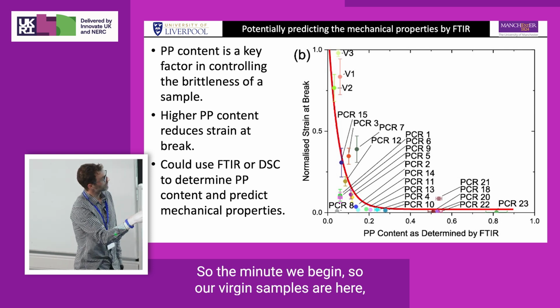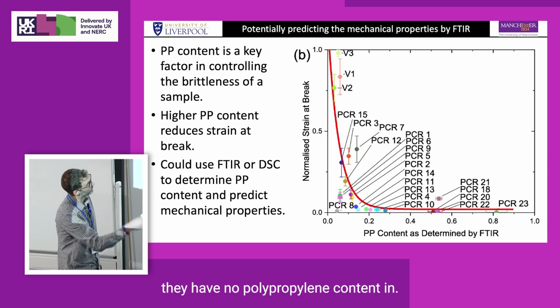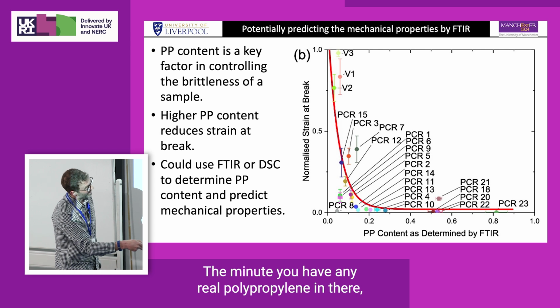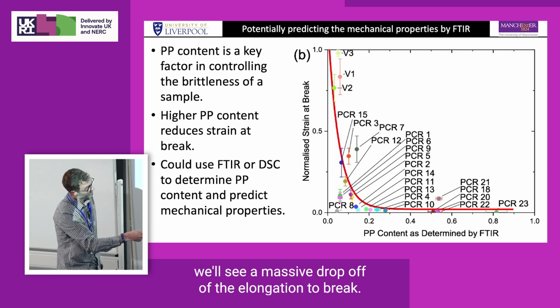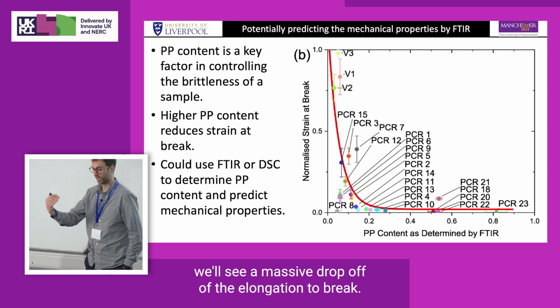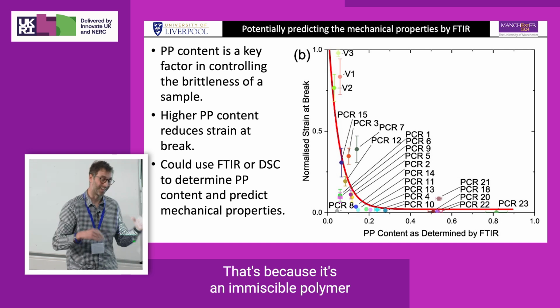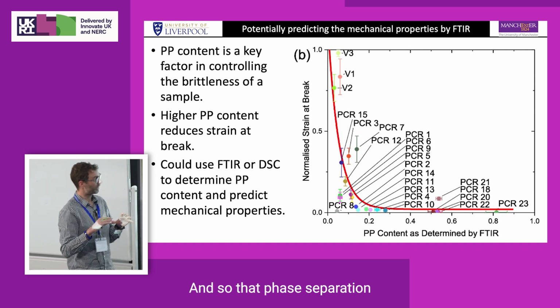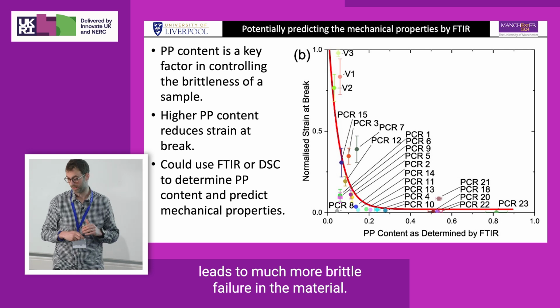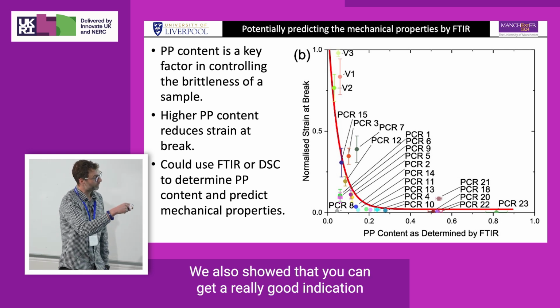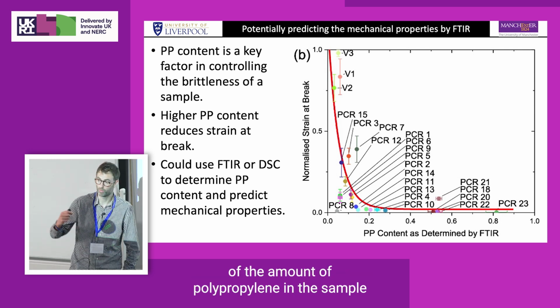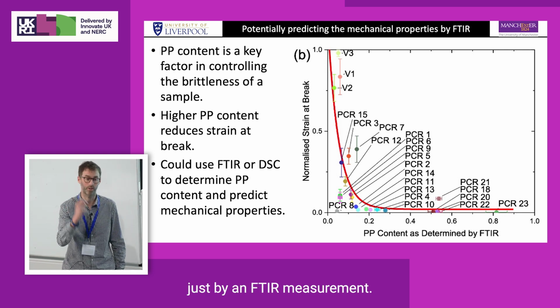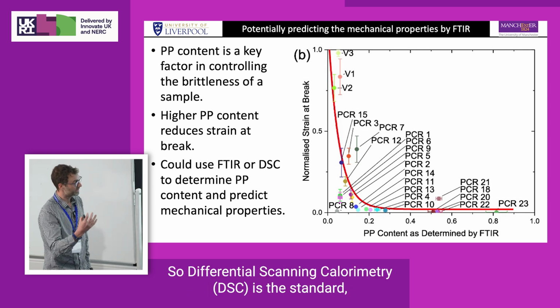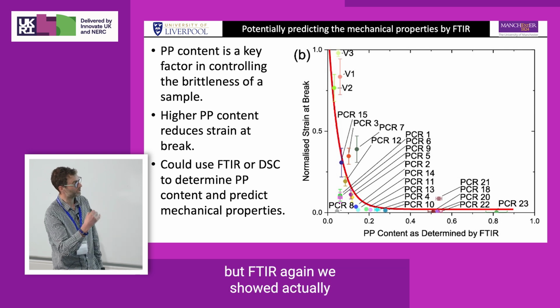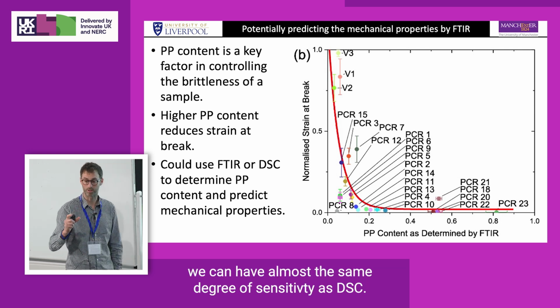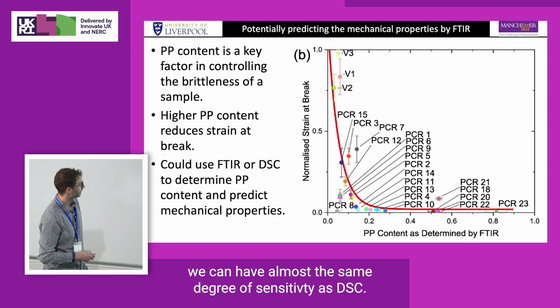So the minute we begin, our virgin samples are here, they have no polypropylene content in. The minute you have any real polypropylene in there, we'll see a massive drop off of the elongation to break. That's because it's an immiscible polymer, and so that phase separation leads to much more brittle failure in the material. We also showed that you can get a really good indication of the amount of polypropylene in the sample just by an FTIR measurement. So DSC is the standard, but FTIR, again, we showed we can have almost the same degree of sensitivity as DSC.